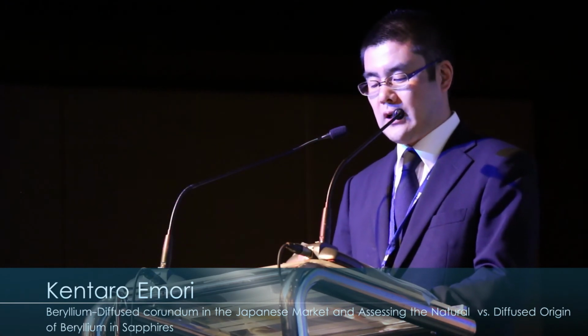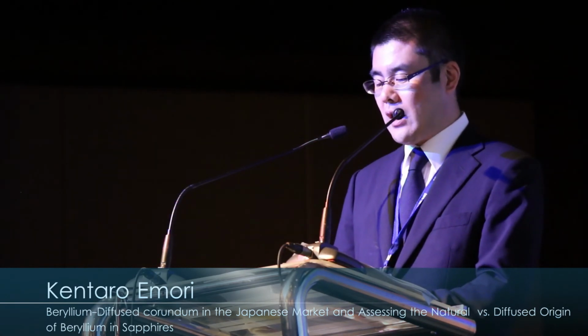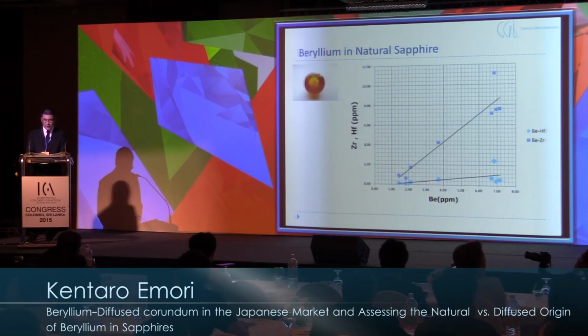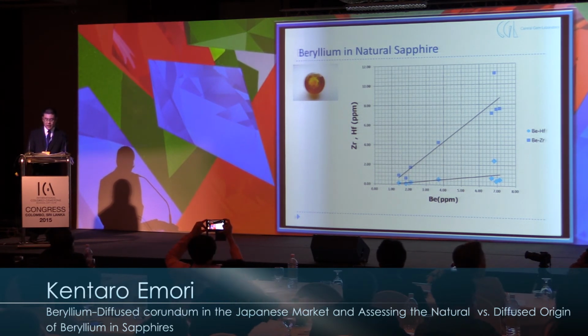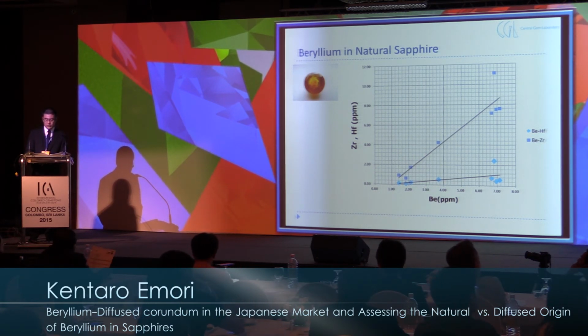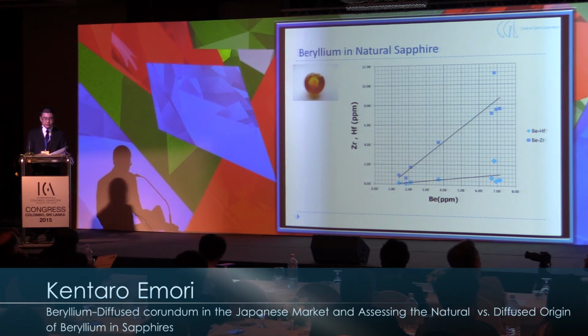It is noted that zirconium and hafnium are also detected. Shen reported in 2009 that there is a correlation between beryllium, zirconium, and hafnium. I investigated the correlation of beryllium, zirconium, and hafnium that were found in this corundum, which were proved to be in a good correlation.